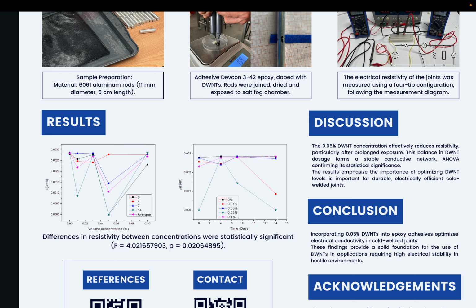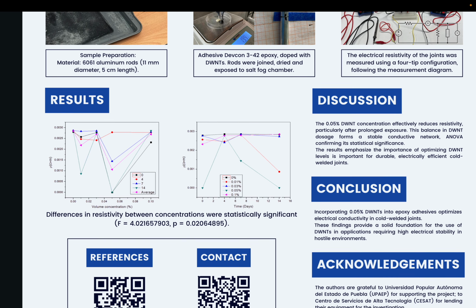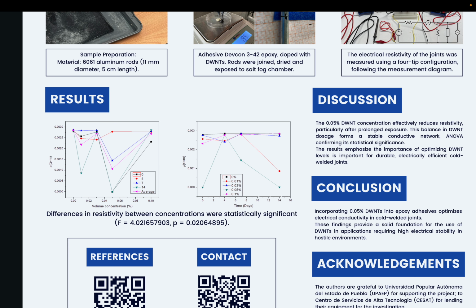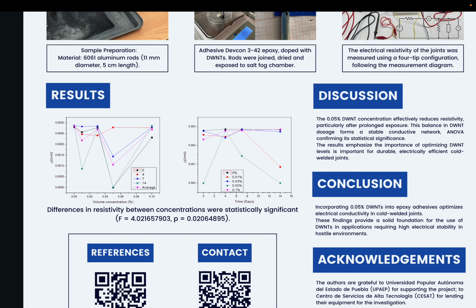On the other hand, higher concentrations, like 0.1%, did not significantly improve the resistivity compared to the 0.05% concentration, likely due to the agglomeration of nanotubes, which can limit the formation of an effective conductive network. The consistent reduction in the resistivity at the 0.05% concentration over the 14-day period suggests that double-walled carbon nanotubes not only improve initial conductivity but also provide long-term stability under harsh environmental conditions.